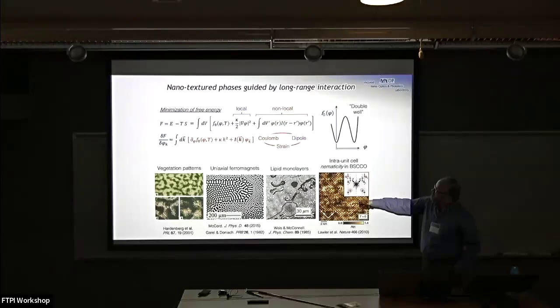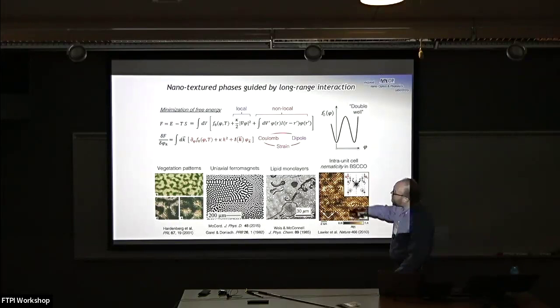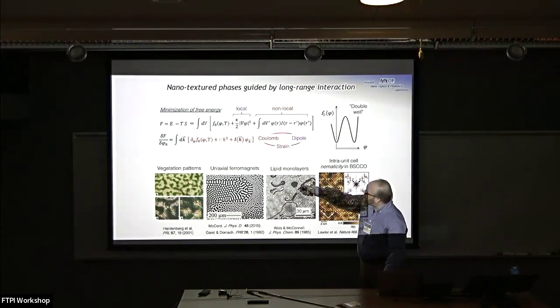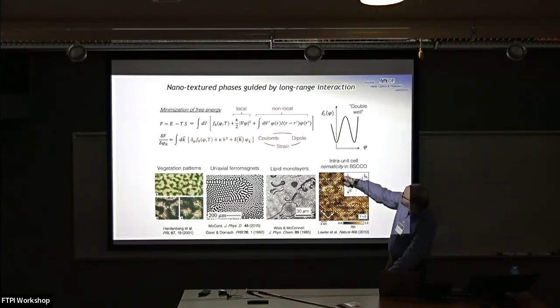Instead, I can vary the free energy with respect to some little wave vector component, some Fourier component of my order parameter. So what do I do? I take derivatives of all of these terms inside of my integral. The important bits being the local penalty for forming domain walls, which goes as k squared. And interestingly, I end up with the Fourier transform of my interaction term.